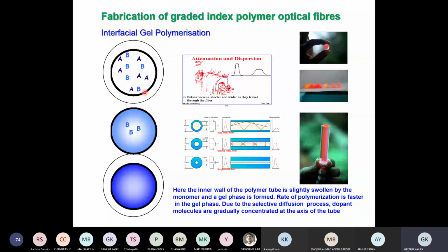Here, what we can see is a cross section of a tube, and this is a polymer already, and inside you have another polymerization happening. So you have the monomer which is to be polymerized, that is A, and another chemical which is B, which is a larger molecule, and they are mixed and heated, and the heating is actually initiated from the sides. This is a tube cross section. The heat is applied from the sides, and the polymerization begins from the walls, and it solidifies, and finally the portion at the axis is solidified.